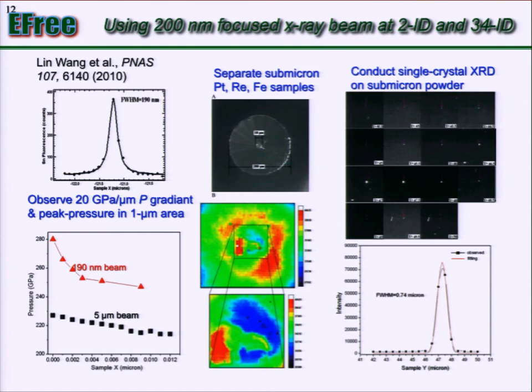But now with the 200 nanometer beam, we will be able to really fine-tune the sample area. Also, once you get to this pressure, how do you know you're at that pressure? You should be able to probe the sample property. For instance, you probe the density, and that's one thing where, with shockwave, you can measure the pressure-density relation. So with a 200 nanometer beam, you can start to see different areas to probe different samples, and also with emission spectroscopy, you can do chemistry there, and you can measure the pressure.